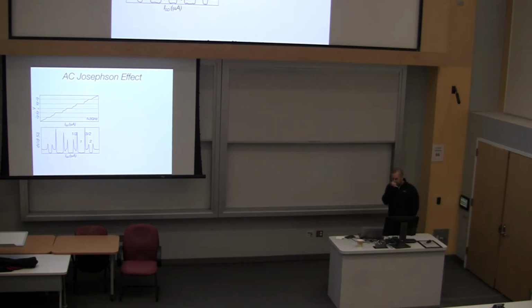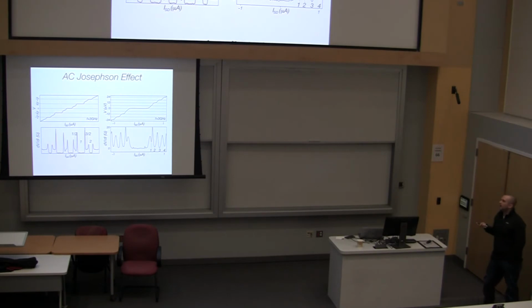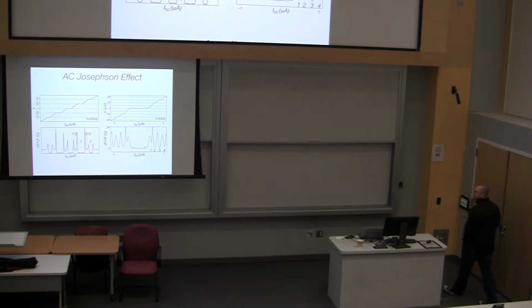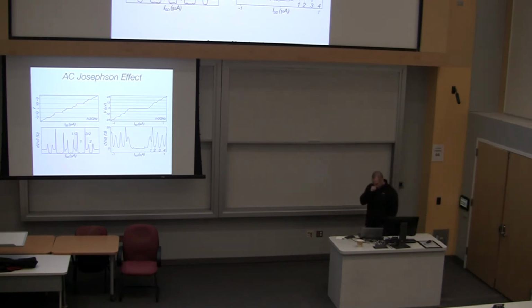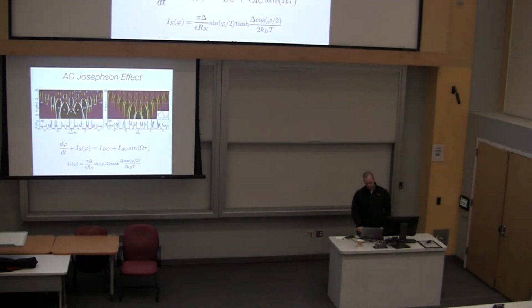One of the things I like a lot about lead-doped tin telluride topological crystalline insulators, compared to, say, bismuth selenide, is we can actually turn off what is expected to be a topological state by tuning the doping of lead. And so we can look at just a lead telluride device and see what Shapiro steps it gives. What we find is that we only see features at integer values of these steps, and for the frequency and bias ranges we played with, we never saw any subharmonic steps in the lead telluride. So it's our first indication that something interesting about the novel surface state is contributing to the Josephson current in these devices.